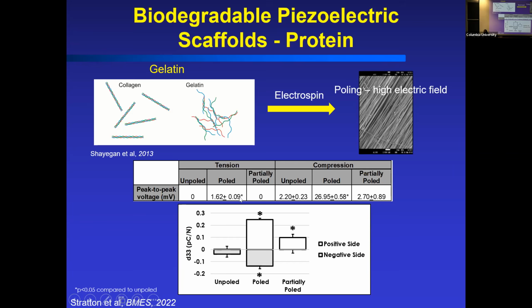So I'm just going to put my arrow here. All right. So if we mechanically perturb those scaffolds in tension for when we pole it, we're getting an output of about 1 or so millivolts. In compression, we see a much higher amount. So we're getting almost on the order of 30 millivolts out of these materials. When we partially pole, you don't necessarily get that in tension, but in the partially poled, you're getting some in compression. We also see the unpoled, right? At least in the fiber form, we are actually still getting some charge out of that.